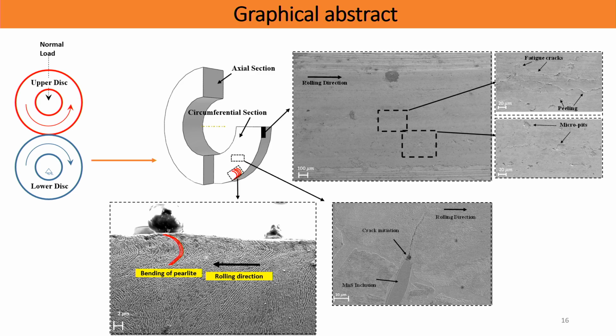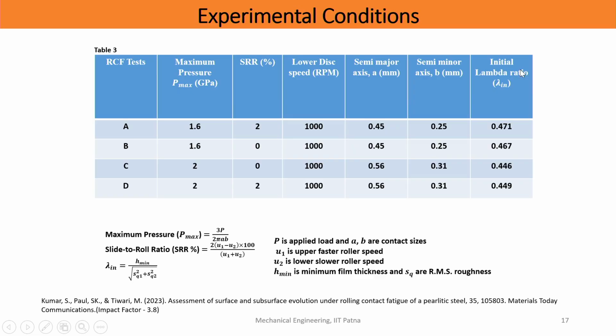Now, what we see here is that there is the bending of the pearlite, and if the slide happens, if the slide ratio is higher, this starts cracking, and you will get a lot of cracks coming up to the surface. Okay. And so, the rolling direction is like this. The cracks will form like this, which we will see very soon, and you start having micropits forming, fatigue cracks. We will see more pictures now. So, just to get you into this, probably I should have told you before, this is the lambda ratio we maintain, 0.467 for boundary lubrication. This is the maximum Hertzian pressure we have, SRR of 2 and 0%.